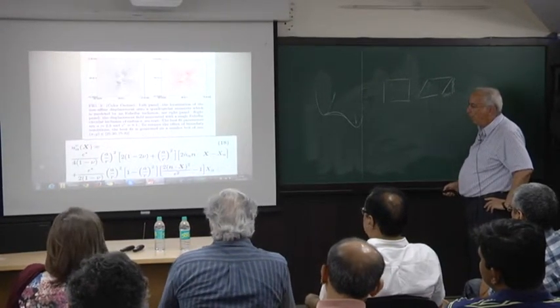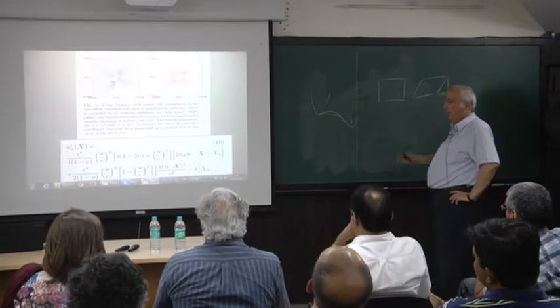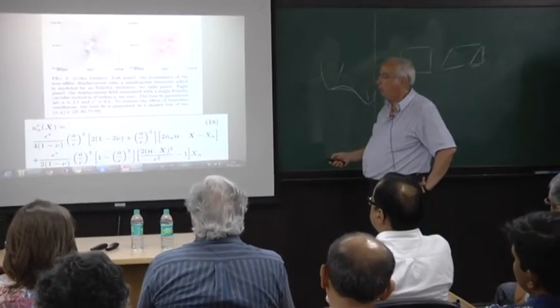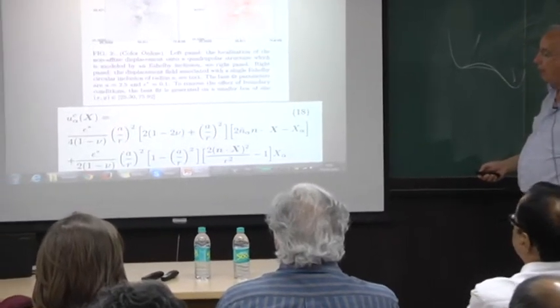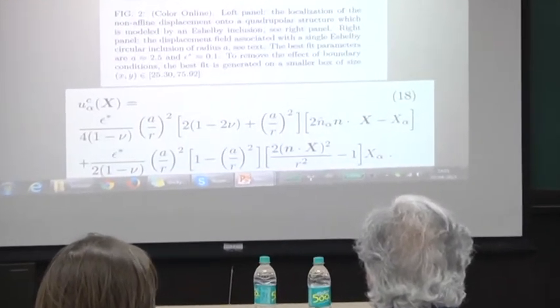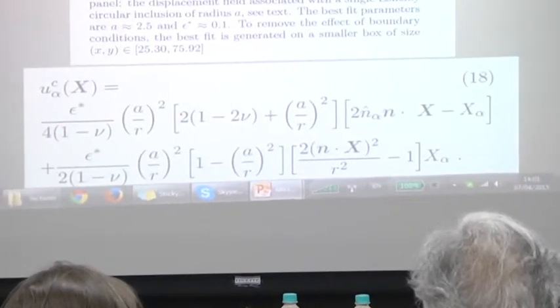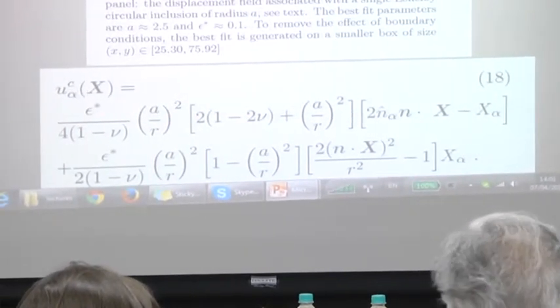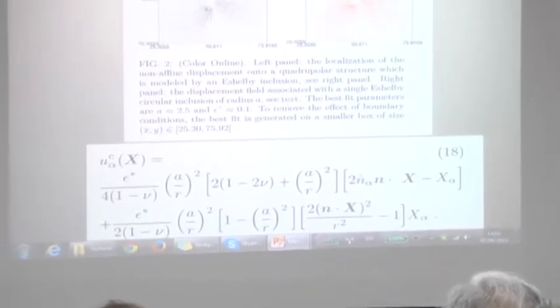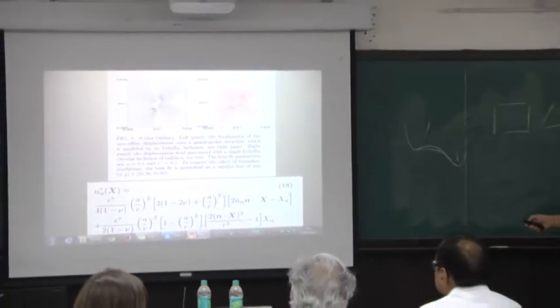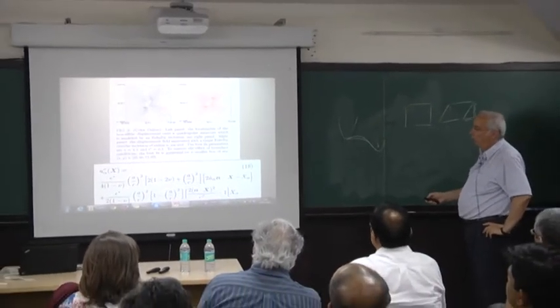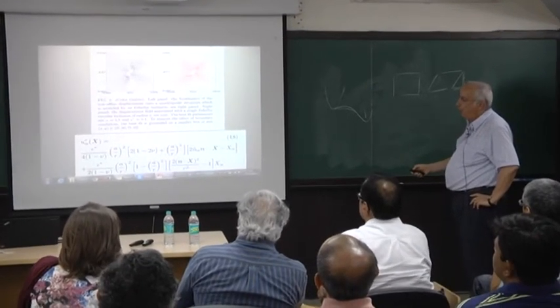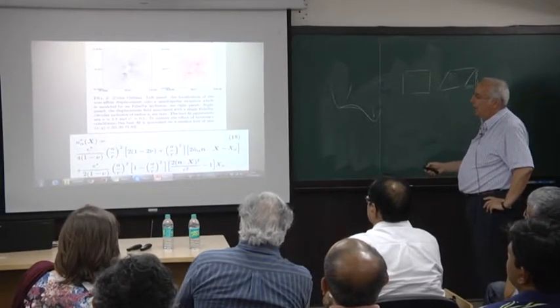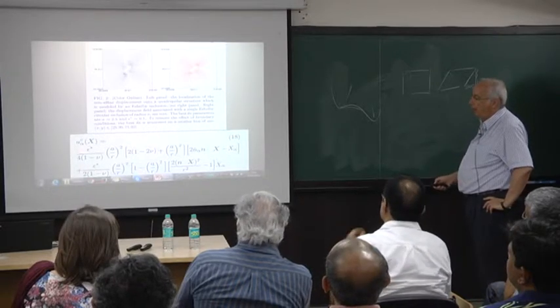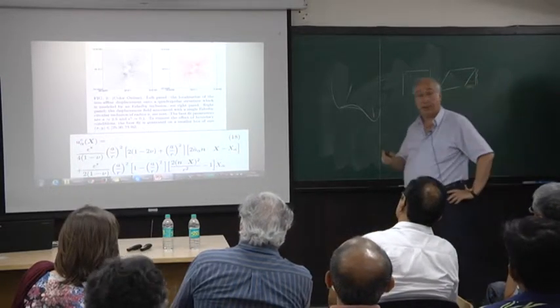You don't need to remember all the details here except that there are two parameters in this problem. The two parameters are the core size, A, which is the core of the Eshelby solution, and epsilon star, which is the eigenstrain of this problem. Otherwise, everything else is in the geometry, and if you plot this, you get this, which by fitting to your numerical data for your system, you can get a very good approximation to the eigenstrain and the core size. I want to stress these are non-universal.